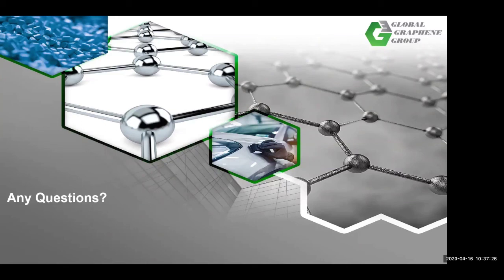For the through-plane, like we introduced to the audience, we can offer the AT1100 and also the thermal paste. These products are targeting the through-plane, and traditionally the through-plane thermal conductivity requirement is basically to lower the resistance between the heat source and the heat sink. So both of these products, AT1100 and our thermal paste, can deliver very low thermal resistance. Then you can better dissipate the heat in the Z direction.